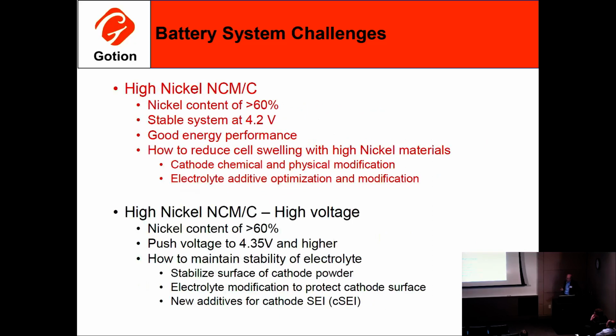The systems we're working on now that are coming up, which I think are important to us, are the high nickel NCM materials. This is 60% and higher, so 622 and 811 type cathode materials, and they're good at 4.2 volts with good energy performance. The challenge with these is, as most people know, nickel is a good oxidation catalyst. Inside of a battery, that's a bad thing. You oxidize electrolytes and other components inside, and then you get gassing, which causes cell swelling and loss of contact inside the cell, and then your performance goes down from there.